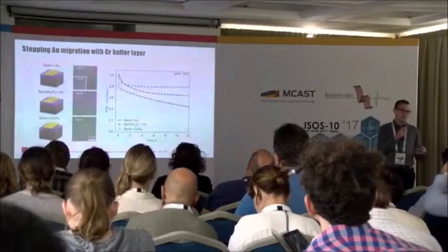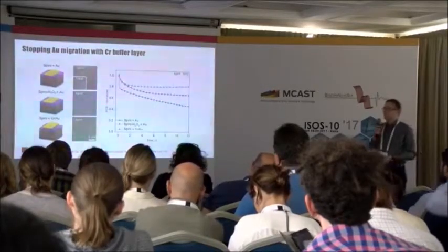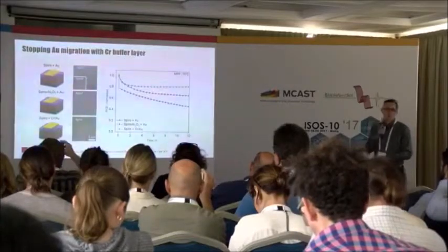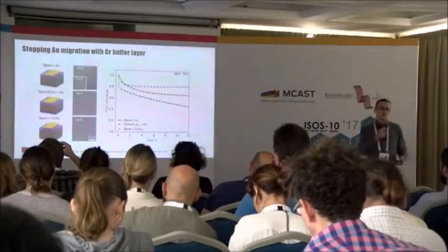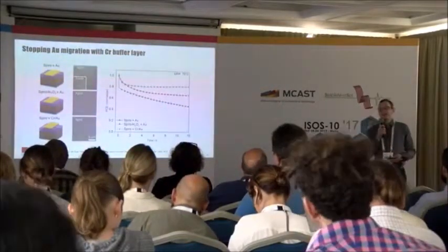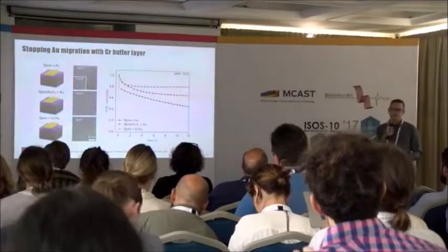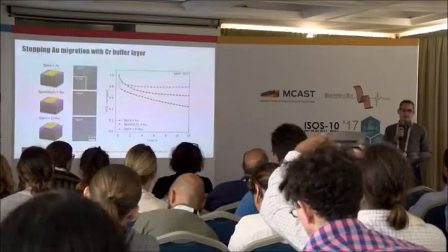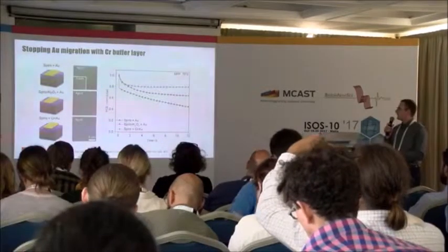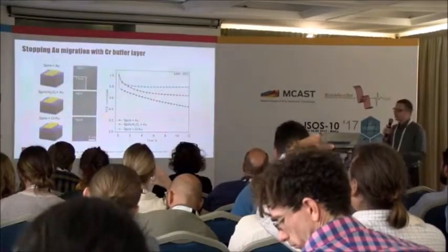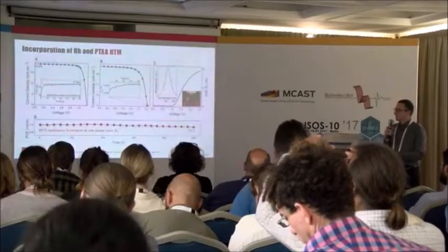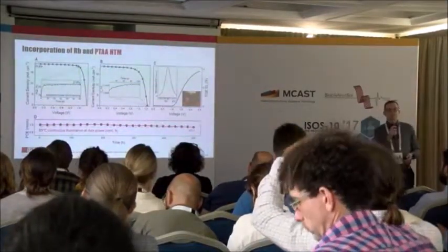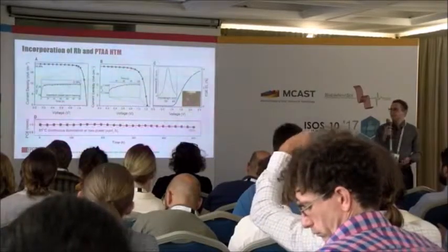So very quickly, I'm just going to mention that we looked at the spiro under the peeled gold electrode. It's completely porous. We tried to fix this problem, successfully, by introducing a chromium interlayer, an old trick from the semiconductor industry. It stopped the gold diffusion. It came at the expense of efficiency. It went down from 20 to maybe 15%. So a trade-off.